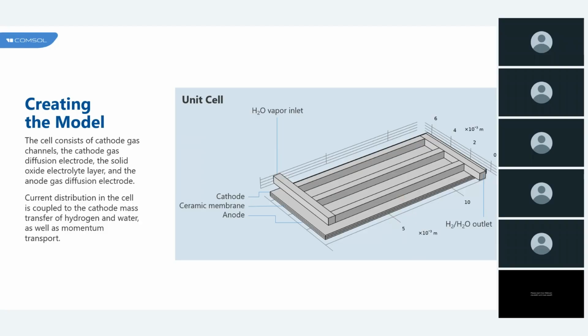This detailed setup lets us capture key outputs like local potential gradients, temperature fields, and gas species distribution. With this information, we can identify the hot spots, non-uniform current density regions, and areas prone to degradation. This is critical insight for optimizing the SOEC performance and durability. Once this unit cell is modeled, we scale to the system level, tracking gas flow and velocity and species transport under real operating conditions.